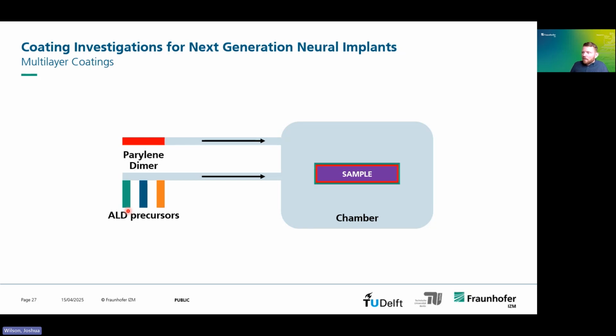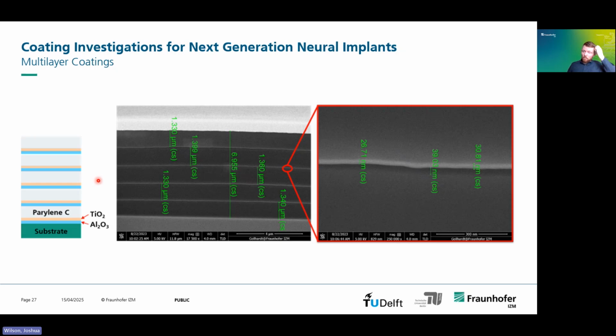And what we can then do is add these layers on top, and we can just keep building more and more complex arbitrary stacks of these layers. Now, to explain a little bit the concept behind this, here is an example of our Parylene ALD films. So we have a substrate, then we have some aluminium oxide, some titanium oxide, and some Parylene C, and this is repeated 5 times. And then you see in the cross section here that is with SEM, that the dark layers here, these 5 wide dark bands, which are 1.3, 1.4 micron thick, are the Parylene layers. And then these very thin lines in between, if we zoom in, these are the 2 ALD layers.